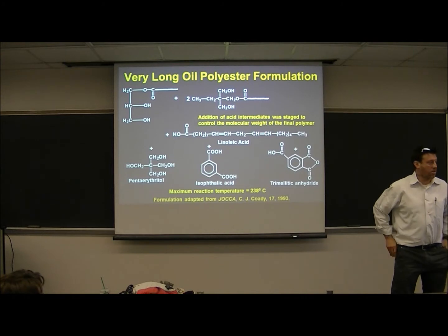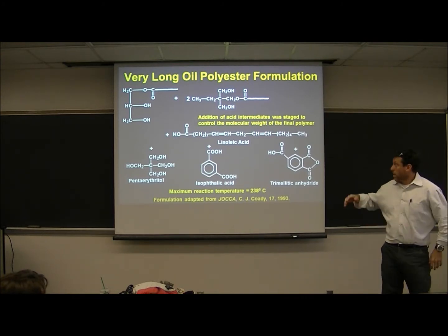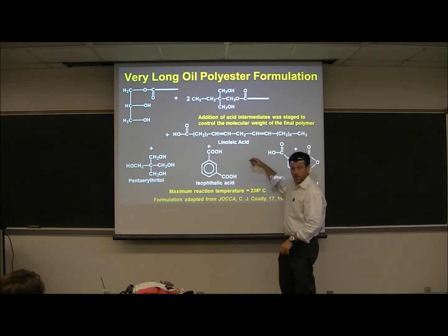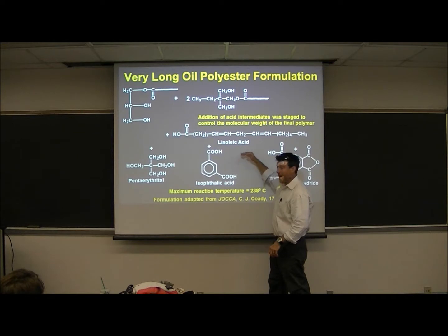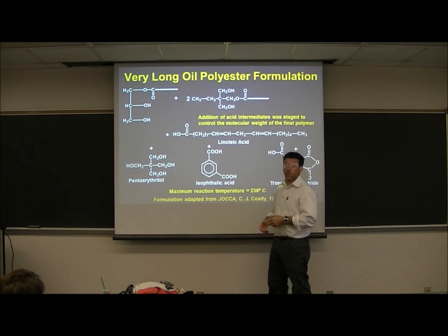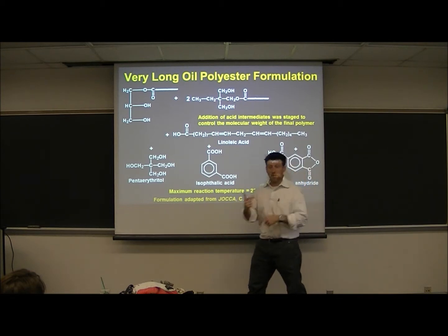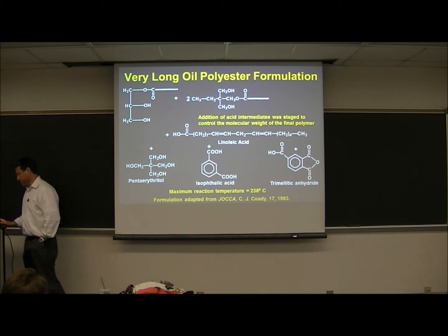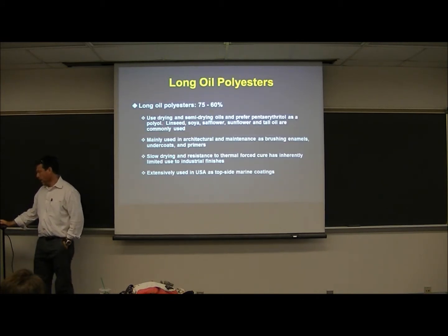There are some important parts to that in the mechanistic part of it. Ultimately, those peroxides would dissociate to form ether linkages, where you get a CO radical plus a C radical, and you form ether linkages. Ultimately, when you were starved of oxygen because you had vitrified, you would get C radicals that would combine, and you'd make methyl bridges or methylene bridges. Okay? But that's the autooxidation process. All right.